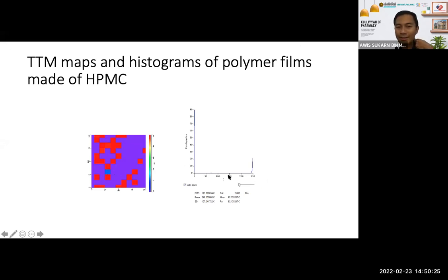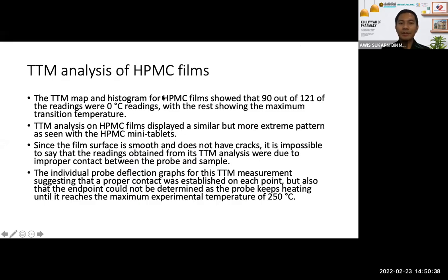And then when we look at the histogram here, you can see 90 points are basically at 0 degrees, and the rest is at 250 degrees. So based on the TTM map and the histogram of the HPMC film, it showed 90 out of 121 points were recorded as 0 degrees, while the rest showed the maximum temperature transition, which is 250 degrees. It shows a similar pattern compared to the tablets, but this one is more extreme, because in the previous one there were still a few points between 0 and 250 degrees, but here it's only at 0 or 250 degrees.